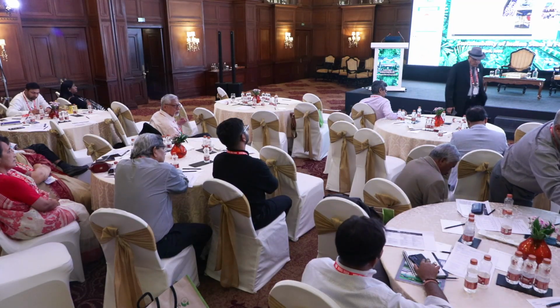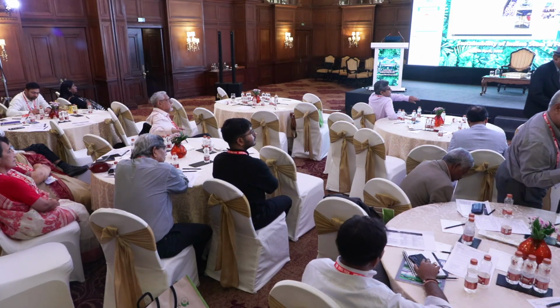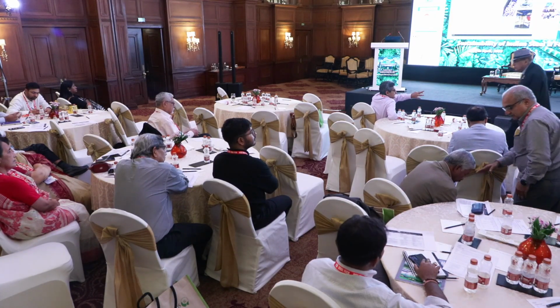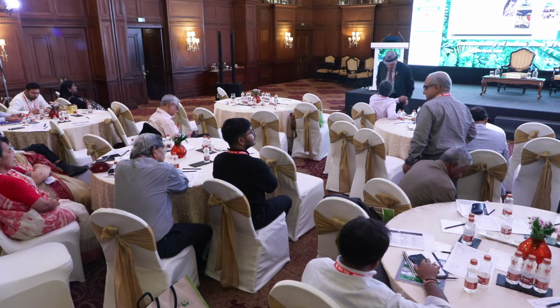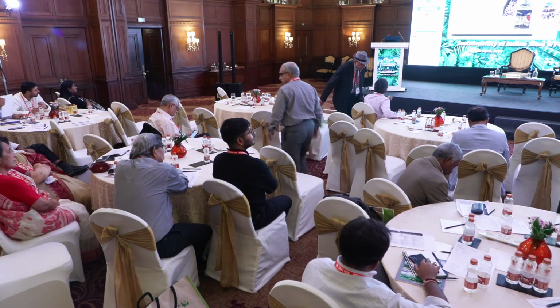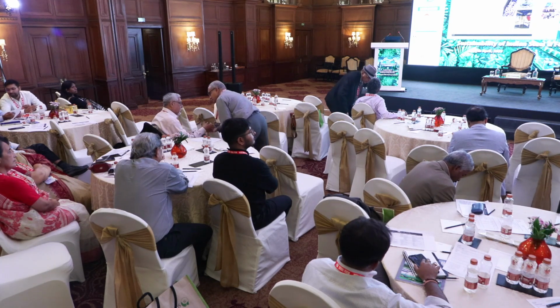We don't want to do that. We want to use the carbon purposes and bring the energy with those electrodes, Söderberg electrodes. And the closed melting furnace, we don't want the leakage air, ingress air to burn our valuable reductants, metallurgical coke. So that's why the closed furnace and this feed with the preheating. And we are all the time measuring almost 100% carbon efficiency for the process.